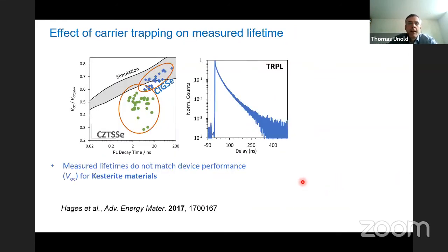So more things that can be problematic is this trapping issue. What we did some time ago is we looked at kesterite solar cells, the relation between VOC and the lifetime, and we found this large discrepancy. Here is shown in gray what you would expect from theory or simulation, and these are the data points that were found for kesterite and here for chalcopyrite solar cells. For chalcopyrite solar cells, it was mostly okay. So you measure VOCs that are expected from a measured lifetime and from the simulation, but in kesterite it did not.